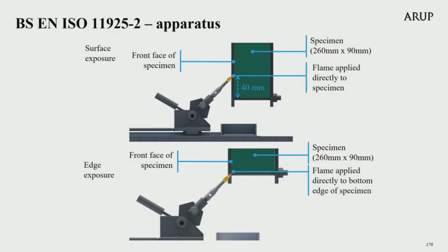Two different exposures are used: surface exposure and edge exposure. A surface exposure test must always be undertaken. Edge exposure tests are only undertaken if the edges can be exposed under end conditions. Therefore, if in the envisaged end-use application, direct flame attack on the edge cannot occur, the product does not need to be tested. When a surface exposure is used, the flame is applied 40 millimetres up from the bottom of the specimen on its front face. A reference line is marked on the sample, and I will show you this on the next slide. When an edge exposure is used, the flame is applied on the bottom edge of the specimen.